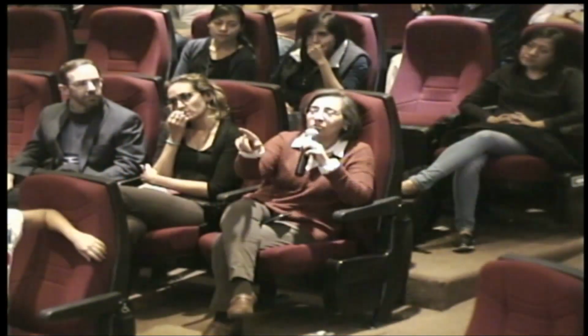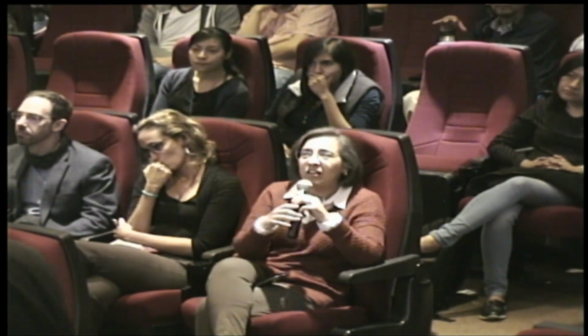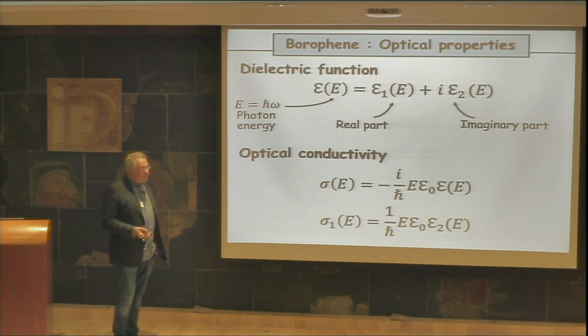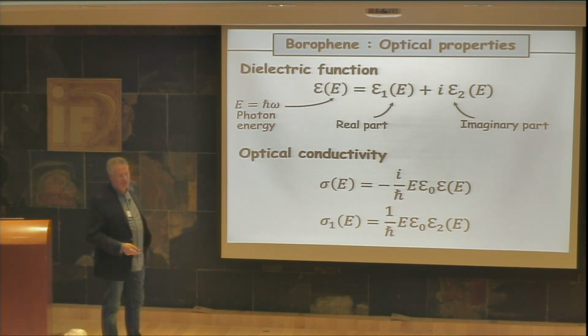I have a simple question. You show a mean-free path of 100 nanometers for this material. But for example, in silver, the mean-free path is about 40 nanometers. How realistic is this? This is difficult to answer because we don't have any possibility to measure the electronic mean-free path in this system, because the substrate is metallic. There will be some interaction with the substrate, so it's not really possible to have access.